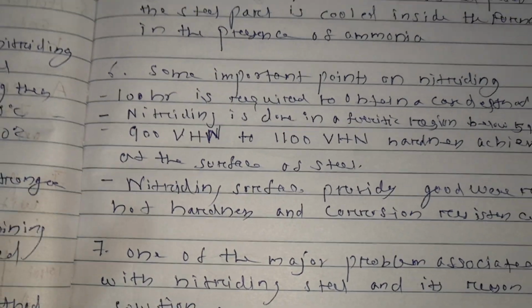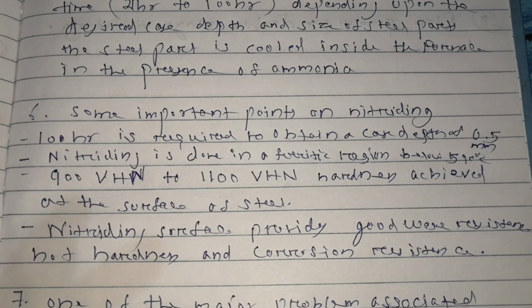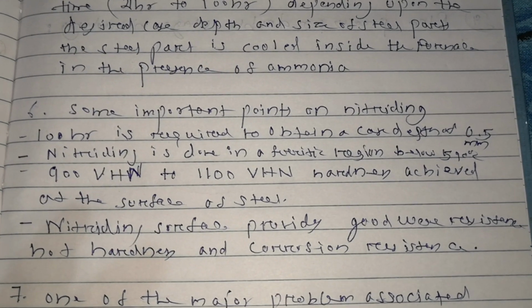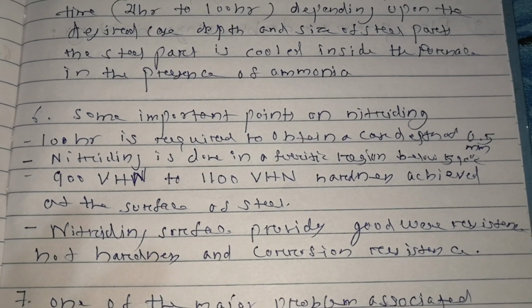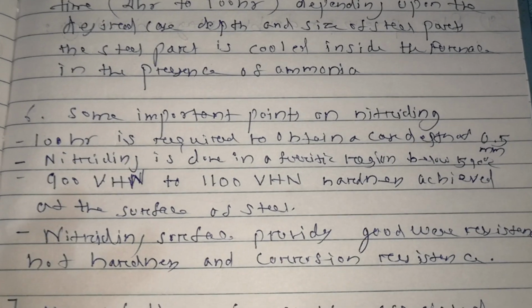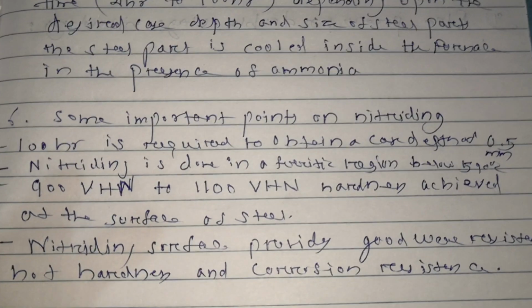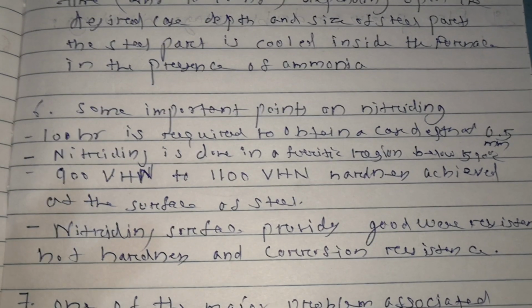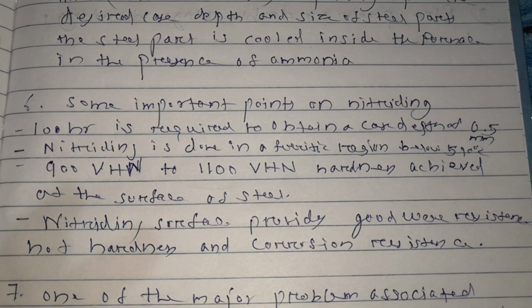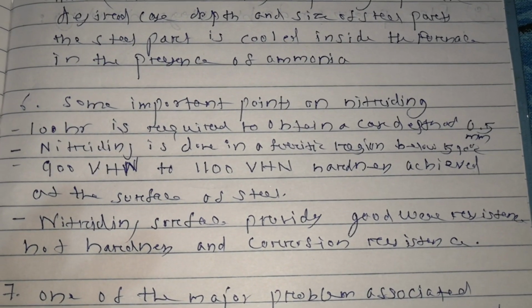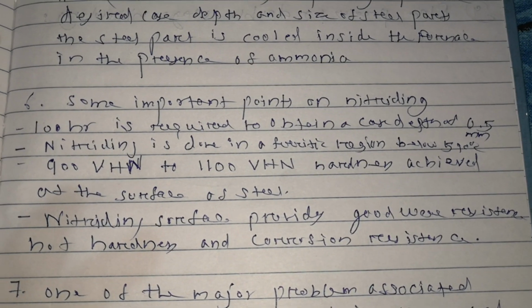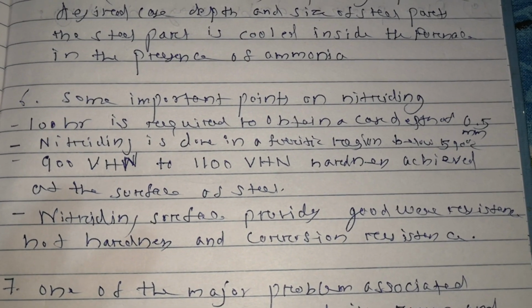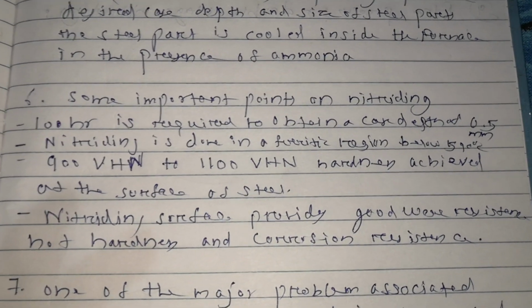Now we'll discuss some important points regarding nitriding. The first important point is 100 hours is required to obtain a case depth of only 0.5 mm, and nitriding is done in a ferritic region below 590 degrees centigrade. Basically carburizing is done in austenitizing region, whereas nitriding is done in ferritic region.